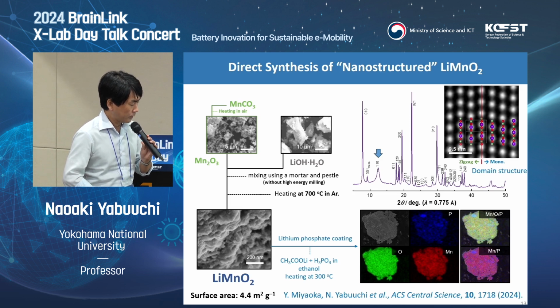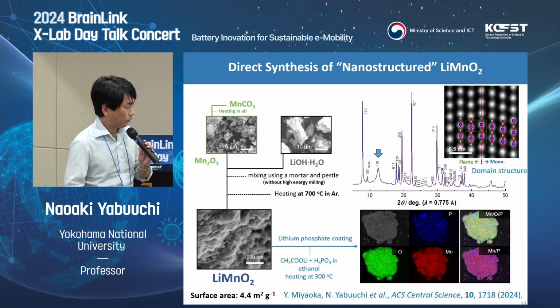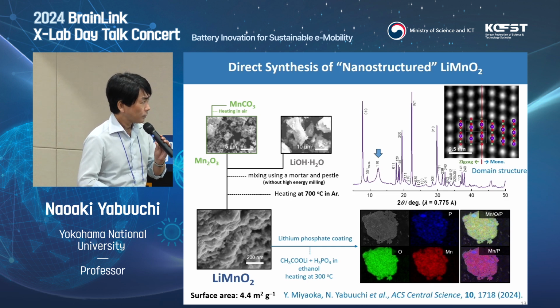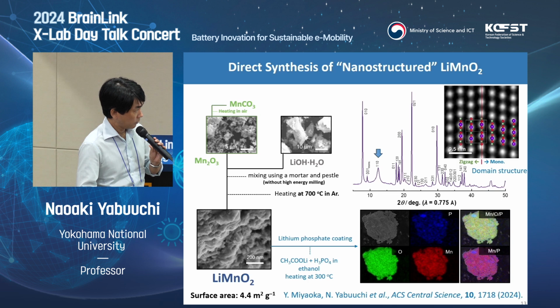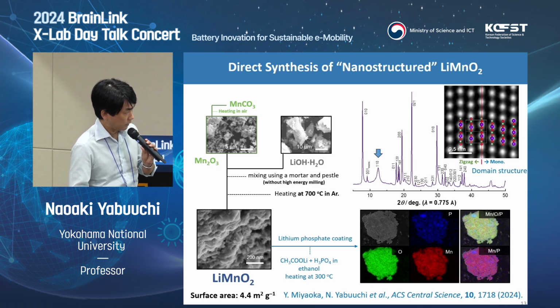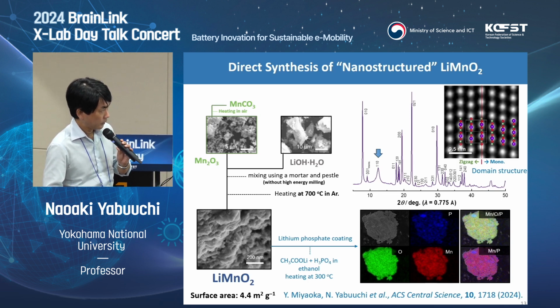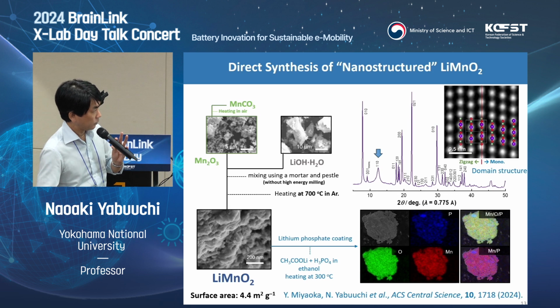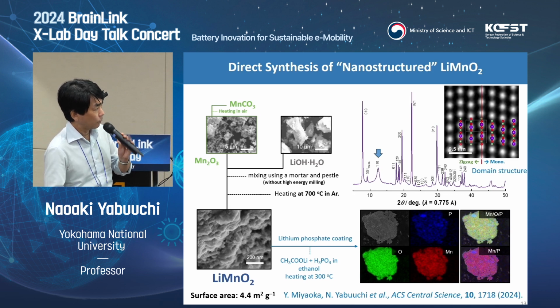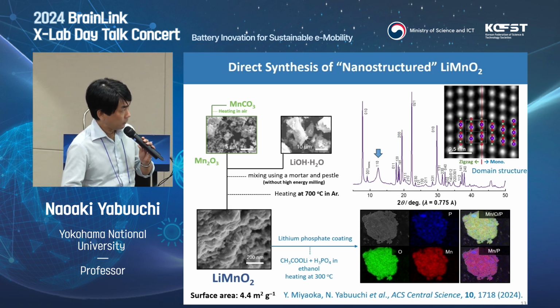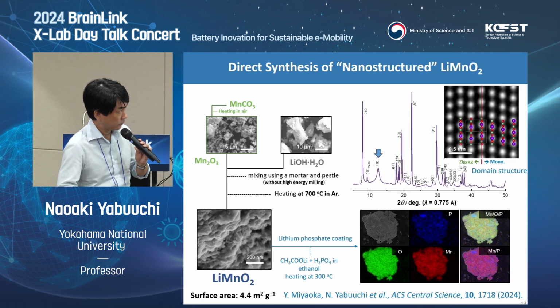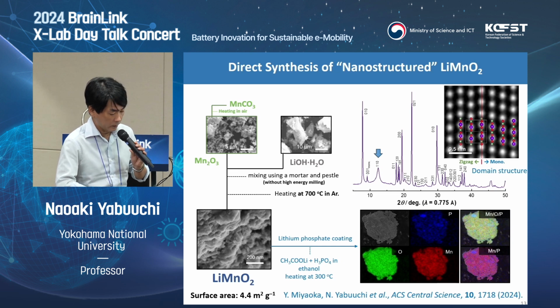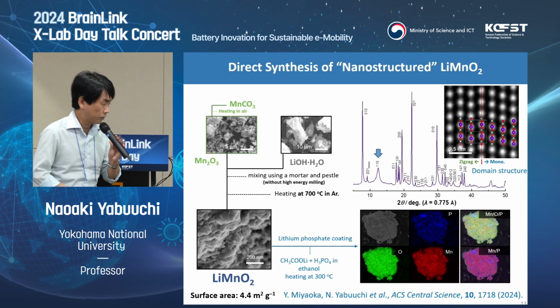So an important point is the surface area is relatively large, 4.4 square meters per gram. And also this 110 diffraction line is very broad. This is because of the presence of stacking faults or domain structures. Some thermodynamically stable regions have a zigzag type layer structure, and also we have a straight type. So this structure is essentially the same as lithium cobalt oxide and lithium nickel oxide.